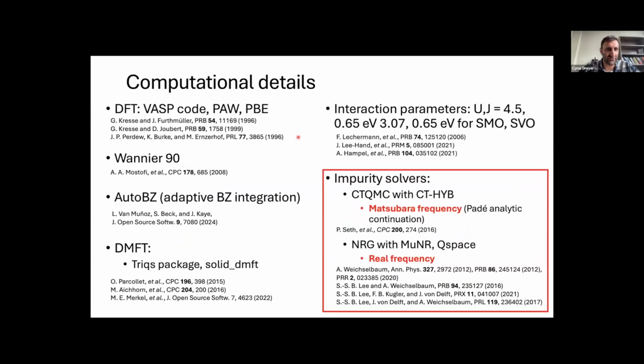So first, I'll just flash the computational details of the calculation. The DFT is done with VASP. One key thing is that we do Wannier interpolation and then adaptive Brillouin zone integration using the AutoBZ code, which was developed here at CCQ. And then for DMFT, TRIQS and solid_dmft. And then one of the key things that we found very useful to gain confidence in our solutions to the impurity problem is comparing these two distinct solvers for the problem at hand.